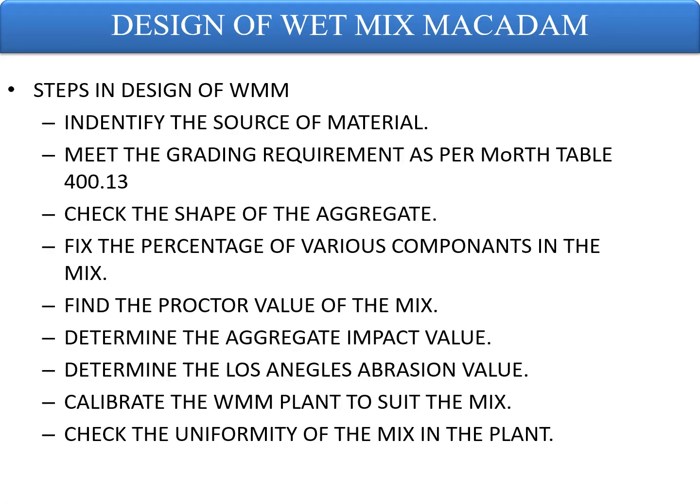The steps required to perform a wet mix macadam or WMM mix are: identify the source of the materials, meet the grading requirements as per the MORTH table 400.13, check the shape of the aggregate, fix the percentage of various components in the mix, find the Proctor value of the mix, determine the aggregate impact value of the mix, determine the Los Angeles abrasion values, calibrate the WMM plant to suit the mixes, and check the uniformity of the mix in the plants.